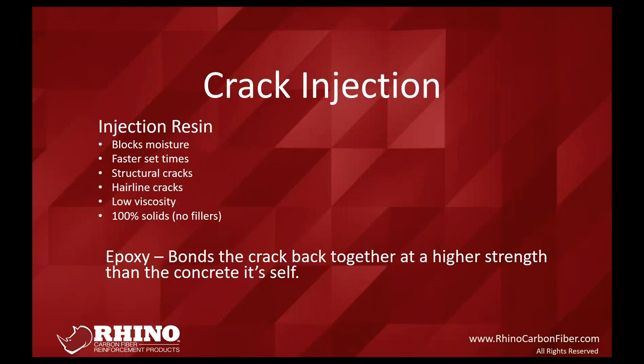The injection resin is extremely low viscosity — similar to the viscosity of water — so it's designed for hairline cracks. It cures solid and has tensile strength equal to the concrete, so it's used for structural cracks and will also block moisture. However, if the crack goes all the way through the wall, the material may just leach out to the outside. In that case, we recommend using polyurethane first as a dam, or excavating on the outside. The true benefit of crack injection is avoiding excavation — you control the water from the inside.